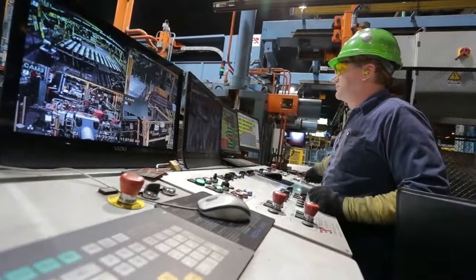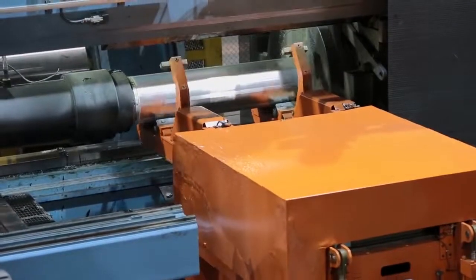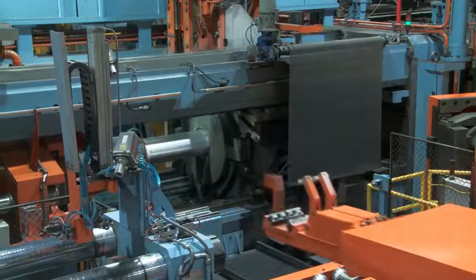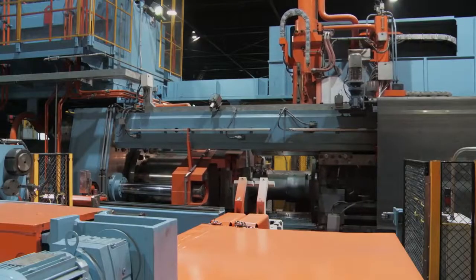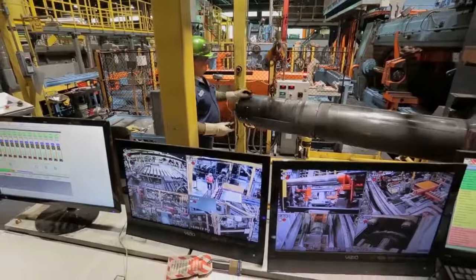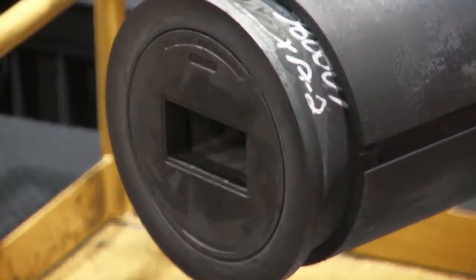Aluminum extrusion is the process of using high pressure to force aluminum material through the shaped opening of a steel die, creating an extruded aluminum profile or shape. In brief, the heated aluminum billet is placed into a steel cylinder or container, then forced through the container by a ram under as much as 100,000 pounds per square inch of pressure. A die stack at the far end of the container holds the opening through which aluminum is extruded to form the desired shape.